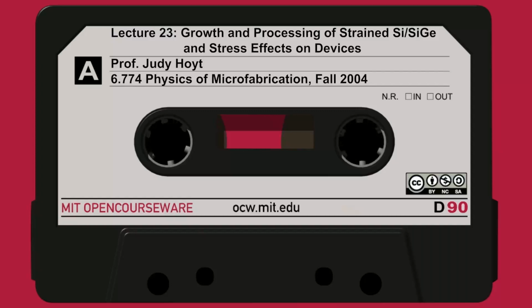That's exactly how SOI is made: they ion implant into pure silicon, and here they ion implant the oxygen into a silicon germanium layer. Toshiba has talked about that. There are some problems, though. For high germanium contents above about 15%, it doesn't work very well. There's another very interesting technique, also from Toshiba, called germanium condensation. They actually start with an SOI wafer.